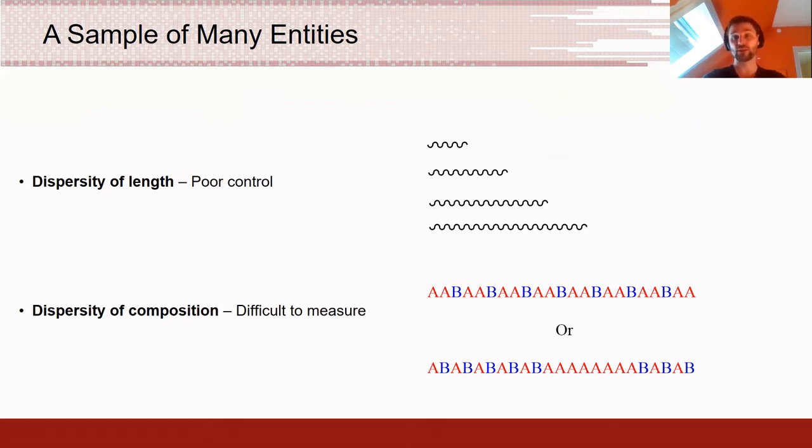So if you have a dispersity in your composition, that is, it is not a statistical distribution of 2:1 throughout the copolymer, that is very hard to discern. This has given rise to fear of batch-to-batch variations, in that some batches behave differently than others. So these are two important measures of which there is a poor control, or at least a poor measure of control in the second case, in styrene maleic anhydride copolymers.